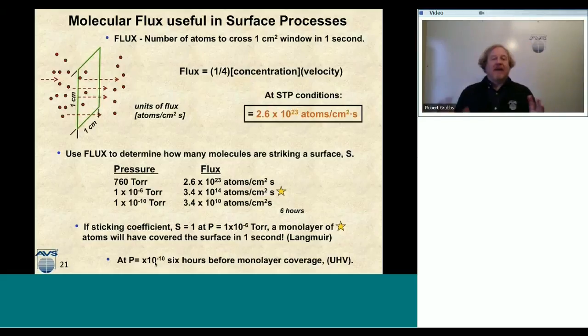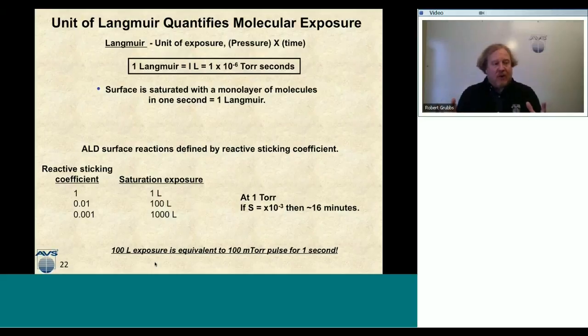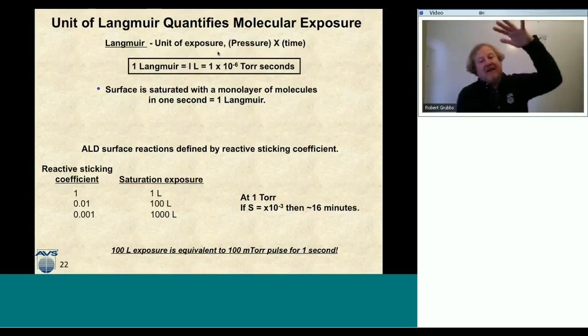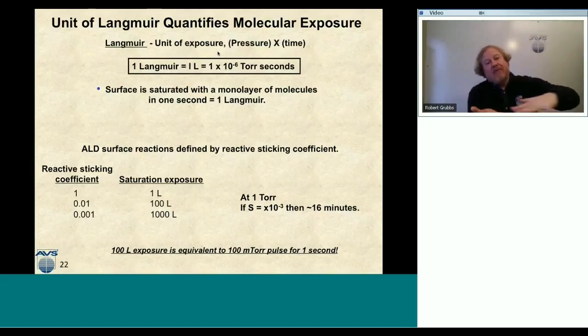Now let's drill down a little deeper into the unit of Langmuir. Langmuir quantifies molecular exposure. So what is exposure? If I put myself in my refrigerator for a certain amount of time, I'm exposed to the cold, and that depends on how much time I'm in the refrigerator and how cold it is. Langmuir, the unit of exposure, is the same thing, except it's the time a material sees a certain gas and the pressure of that gas. This is an important unit in ALD chemistry. 1 Langmuir equals 1 times 10 to the minus 6 torr seconds, because at 1 Langmuir my surface is saturated with one monolayer of molecules in 1 second. That's the definition of a Langmuir.